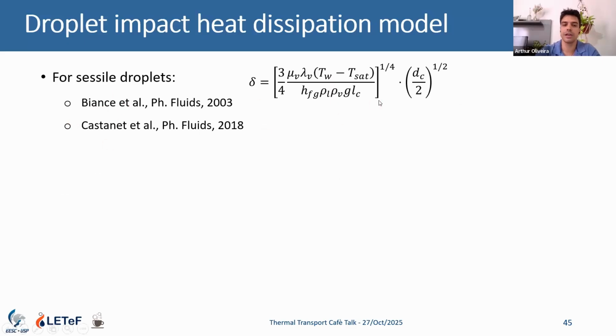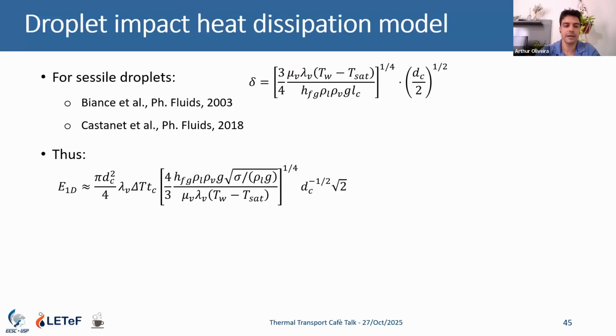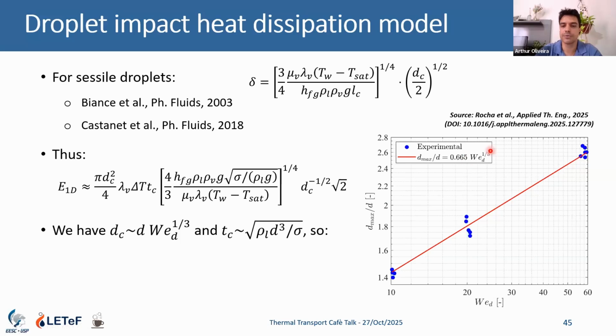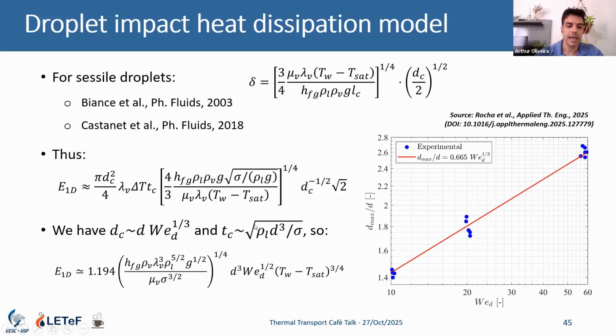And then we have this model here. Let's put that in the equation. And now we have a contact diameter and a contact time model here. So we took our results and we saw it depends on the Weber number to the 1/3 power. This exponent can change a little from the literature, but we have other authors that reported the same power as us. And we used Rayleigh oscillation time here as a characteristic time.